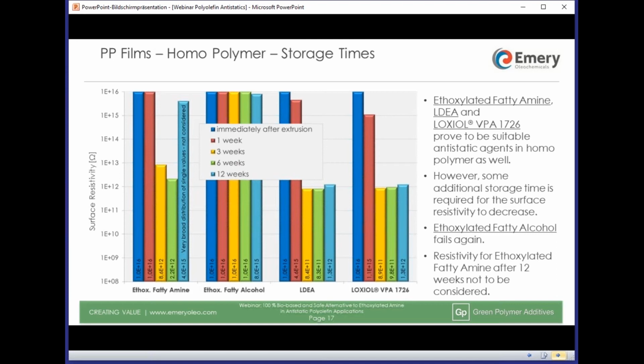After storage for 3 weeks or longer, however, the resistivity level, which is reached by 3 out of the 4 antistatic agents, is comparable and good. Ethoxylated fatty alcohol does not work. Again, I must say. The light blue column for ethoxylated fatty amine on the left-hand side indicates a very high value. This average value for surface resistivity shows an ultra-high standard deviation and should not be considered. But I also did not want to just leave it out. The reason for this high standard deviation, unfortunately, could not yet be identified.